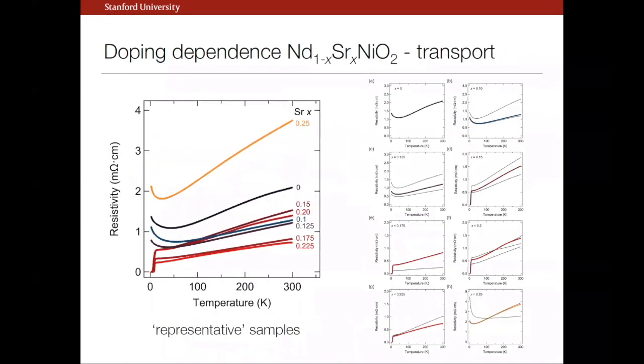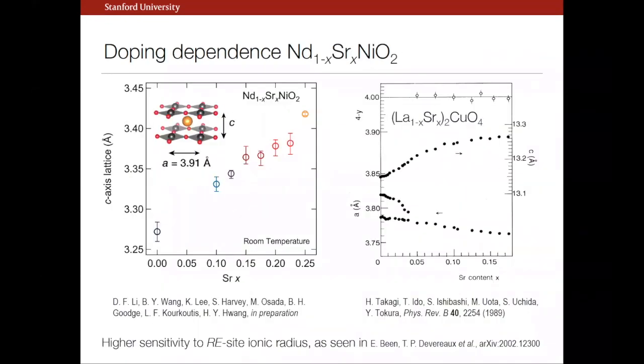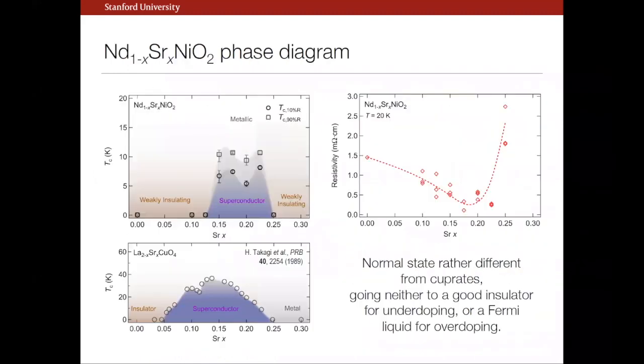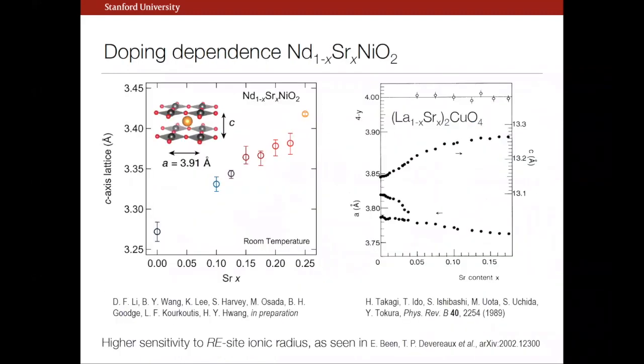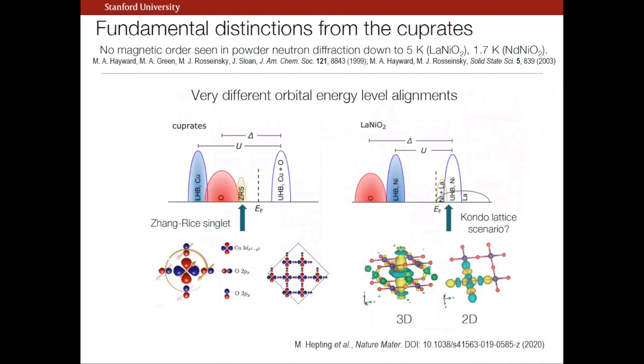The question was, should we view these as quasi-2D? They certainly have a 2D crystal. Okay, so that's not a useful answer. We would love to start probing the c-axis conductivity in any form. What is different here is that this electron-like pocket is quite a three-dimensional like object. This is from Tom's group's Wannier kind of projections. So that aspect should be rather different from the cuprates. But we don't yet have an experimental probe, let's say, of the c-axis response.